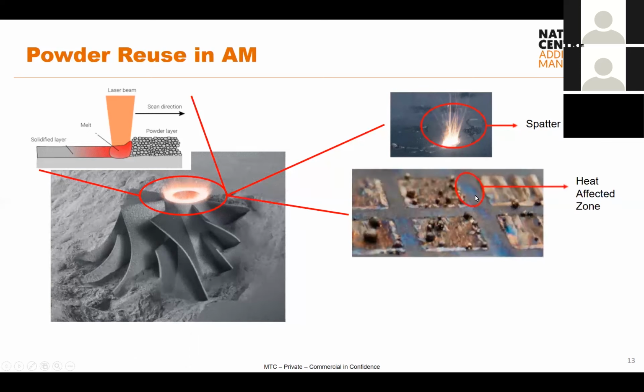The other issue we have is something known as the HAZ, heat affected zone. The heat affected zone is the powder immediately adjacent to the melt piece. So this is powder that's not melted, but it is exposed to elevated temperatures. Because it's exposed to elevated temperatures, again, there's the chance that it can form agglomerates and sinter with surrounding particles, but there's also a chance that it can pick up oxygen from the environment. So again, locally, we're going to have higher levels of oxygen on particles. The heat affected zone, of course, is going to depend entirely on the type of part that you're making, in terms of, say, the surface area of the melt, but also the processing parameters in which you're running your process. So that can be more or less affected.